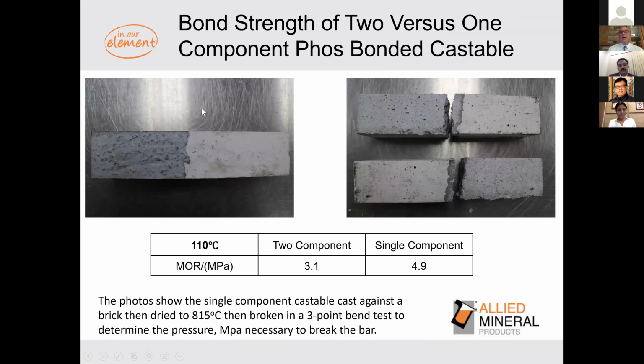The next criterion was the bonding strength. The added benefit when, in the 90s, the Phos bonded two component castables were developed, was that they had the ability to bond like super glue to existing refractory. And so we wanted to make sure we didn't lose that. And again, we're happy to report that when we cast the single component material to a brick and break it in a MOR 3-point bend test to measure the tensile strength of that joint, the single component was just as strong. Statistically, there's probably not much difference between those two numbers, but it definitely was not less bonding strength.